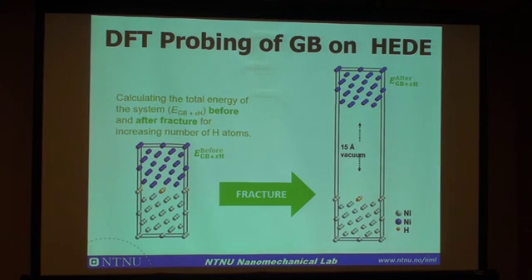So in this HEAP project, we are doing atomic probing on the effect of grain boundary. And here are some examples. We started with the hydrogen enhanced decohesion mechanism. We put the grain boundary between the two crystals, and use DFT calculations to calculate the energy before and after the fracture.